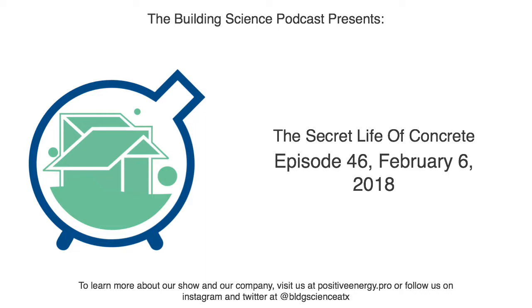I get it. In real simple terms, those ingredients that Lee mentioned come from limestone and clay. When you heat them up and add energy to them, you're driving off carbon, oxygen and hydrogen from those molecules. When you grind that up into a fine powder and add water back to it, it gets the hydrogen and the oxygen back, and it's like a reversible reaction. You put heat in, you drive off those elements, you put the water back in, and it will recombine and try to go back to the state that it was in before.